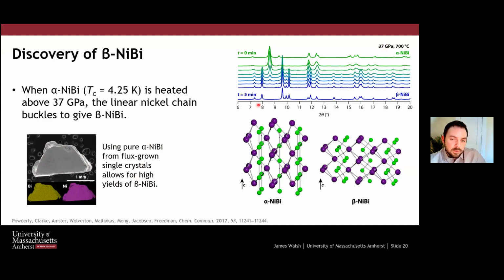So over the course of 5 minutes, we get this conversion from the original, what we now call alpha nickel bismuth, into a new phase, which we call beta nickel bismuth. This is essentially a buckling of what was this linear chain of nickel atoms. What would be really nice is if we could somehow measure the superconductivity of this phase, because these two phases are pretty similar. We might be able to learn something from having this now buckled nickel chain and what effect that has on the superconductivity.